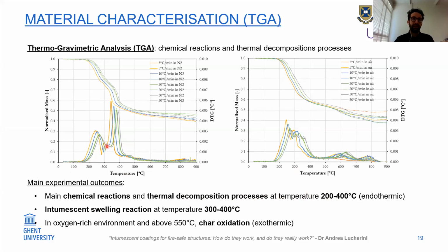So you can see here that the main reactions happen between 200 and 400 degrees, where the first peak is the release of gases and the melting of the coating, and the second one is the intumescent coating swelling reaction, which usually happens between 300 and 400 degrees. And here in oxygen, you have a similar behavior, but the main difference is that you also have some peaks above 550 degrees, and this is typically char oxidation, the oxygen oxidizing the char, and this is an exothermic reaction.